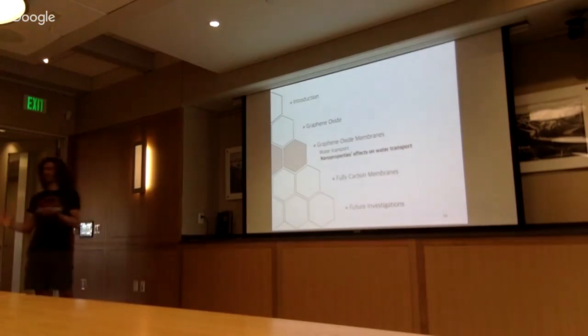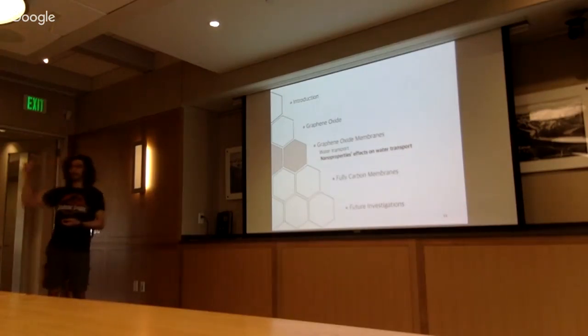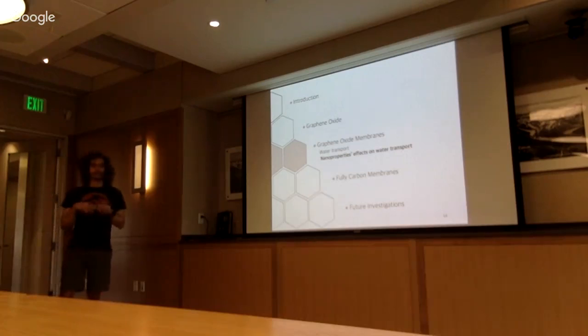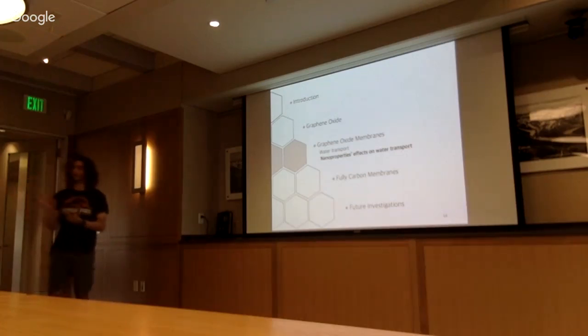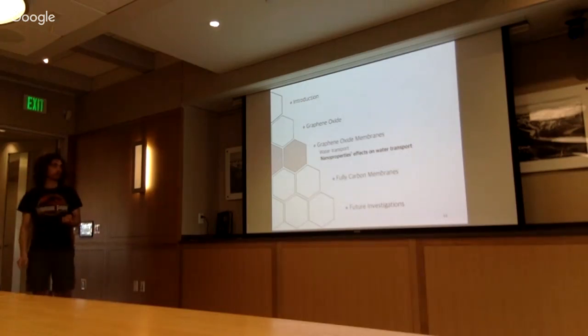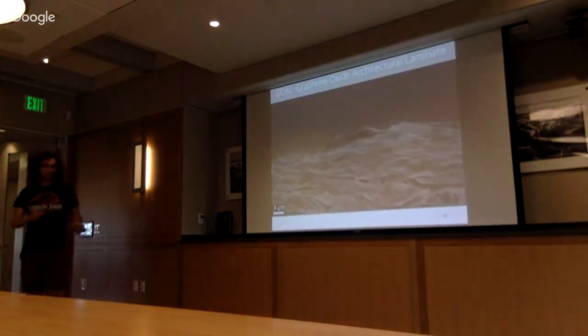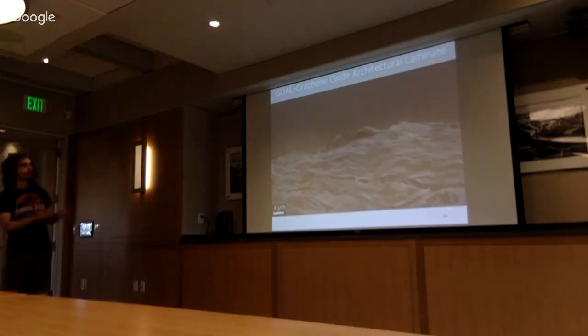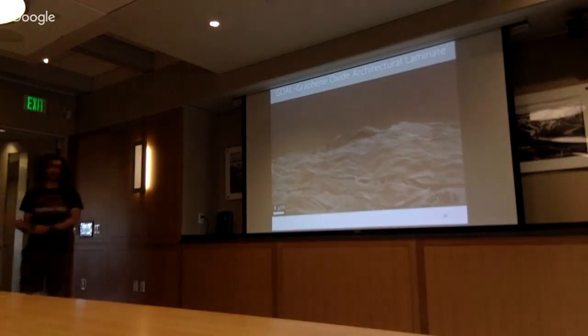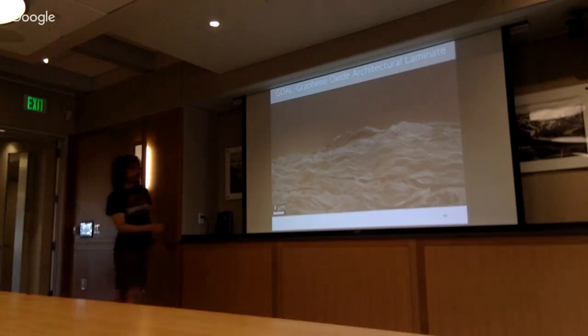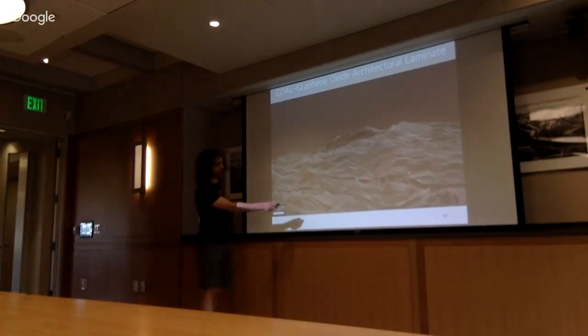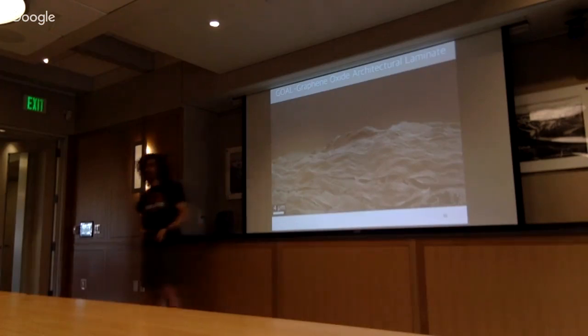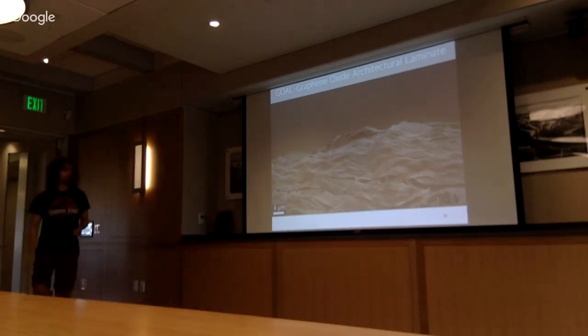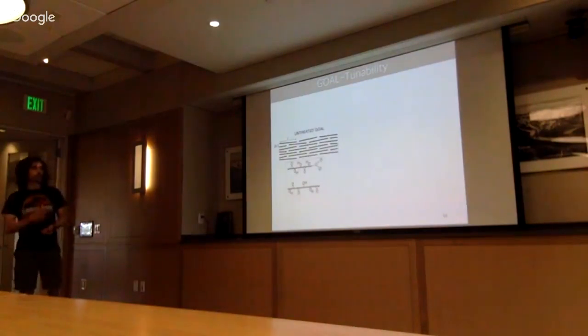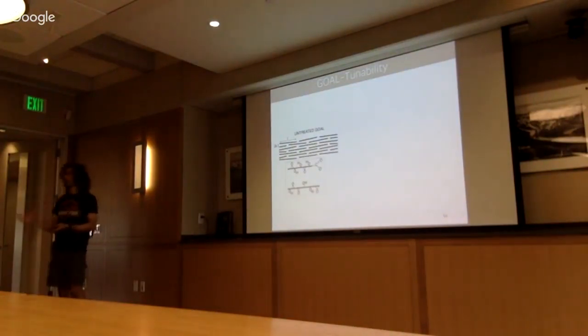And so now that you understand how the water flows in this material, let's do more and see if you can tune the nanoproperties of this material in order to tune the water transport in the material. So what we did, we defined a goal, which is a graphene oxide architectural laminate. Here you see SEM images. Basically, you see here is the thin graphene oxide layer sitting on top of a polymer substrate. And we call it an architectural laminate because what we want to do is change its architecture.